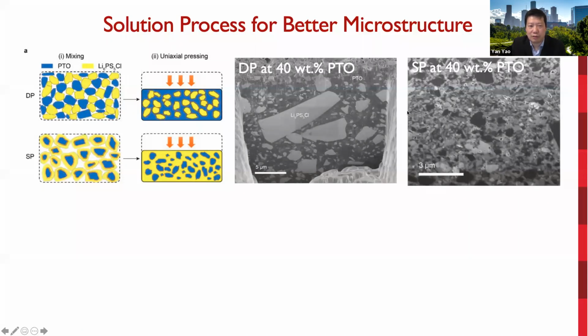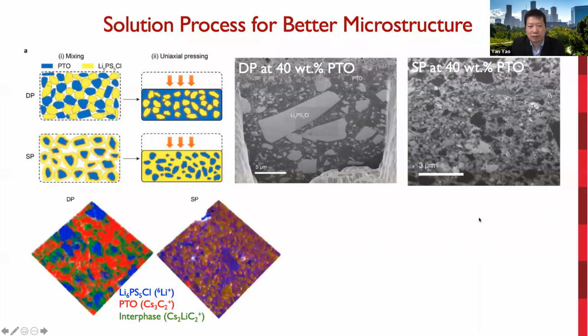So although this is a solution process, we have to dry the solvent off in the oven to make it fully solid state. We also did the ToF-SIMS measurement. The images not only confirm a more uniform spatial distribution of PTO in the solution process compared to the dry process, but also provide molecular information of the interface.